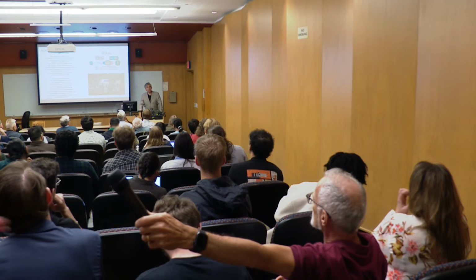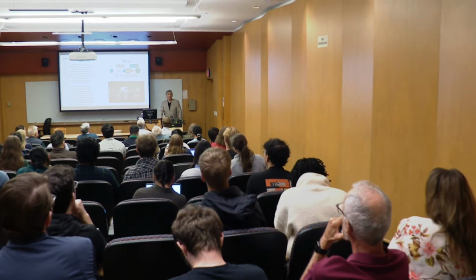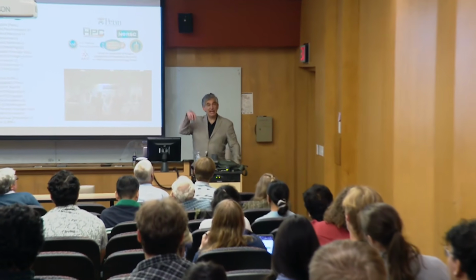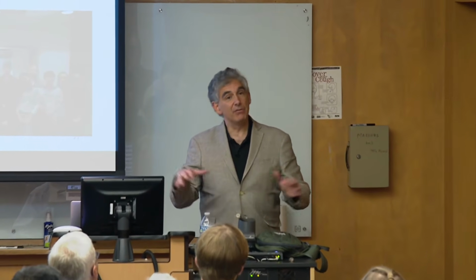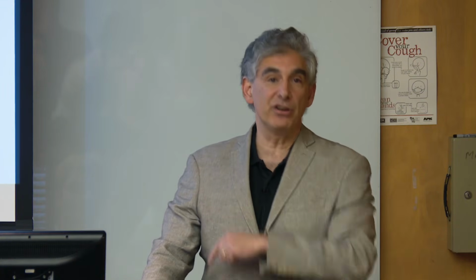Yes. The modulus is not single valued. At the very least, you would need to have out of plane and in plane moduli. The indentation mostly measures the out of plane, and the wrinkling mostly measures in plane, although there's some bending effect that is mixing those up. For the rest of the modeling, I focused on the out of plane, because I think the unloading experiments of the out of plane are the cleanest set of data, because the wrinkling is very sensitive to layers sliding against each other, not the intrinsic compression and stretching of the layer. That would be an interesting further study, but we didn't follow up on that. So the wrinkling is reported, but the modeling that we did was geared toward the Oliver-Pharr indentation part, which we thought was complicated enough, but that was the cleanest subset of the data.